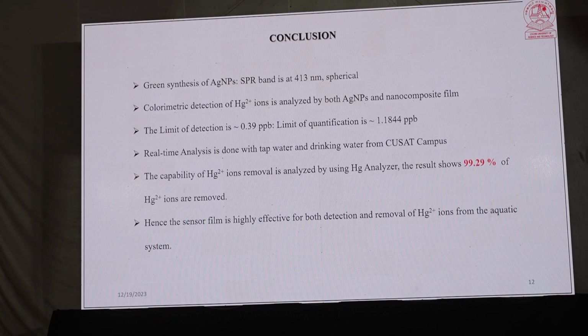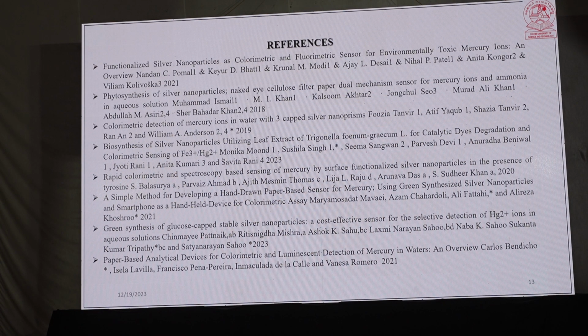And the real-time analysis is also done with tap water and drinking water from the CUSAT Campus. And the capability of Hg2+ ion removal is analyzed by Hg analyzer. We get a better result: 99.29% of Hg2+ ion is removed by using a single piece of composite film. Hence, the sensor film is highly effective for both detection and the removal of Hg2+ ion from the aquatic system. These are my reference papers.